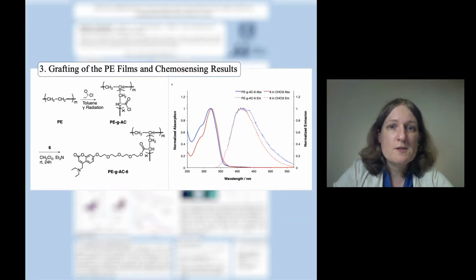On the left of the screen, you can see the scheme for the grafting of the polyethylene films. The films were grafted first with acryloyl chloride using different doses of gamma radiations. Afterwards, they were reacted with the previously synthesized Coumarin derivative. On the right of the screen, you can see the absorption and emission spectra of the Coumarin derivative. It is shown in chloroform as well as in the film. It can be observed that the spectra are almost superposed.